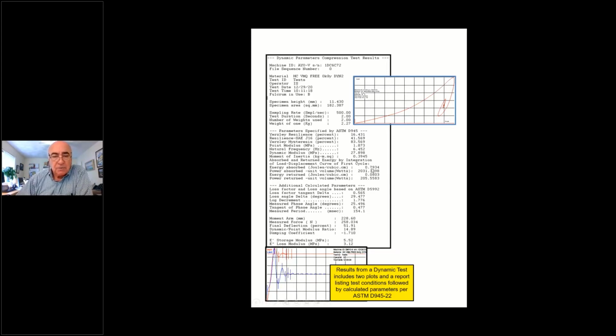There's a 10-to-1 ratio, as you can see. There's a lot of energy being absorbed because it's a damping characteristics, high damping characteristics. Next, we look down at loss energy tangent delta, which is 0.565, referring to a loss angle delta calculated on the basis of ASTM D5992. By the way, I would like to refer to D5992, which characterizes dynamic testing systems under free oscillation and forced oscillation. Our system is a free oscillation system. The forced oscillation system is based on hydraulic, piezoelectric, or other actuators, which really can scan all the way up to a given hertz.